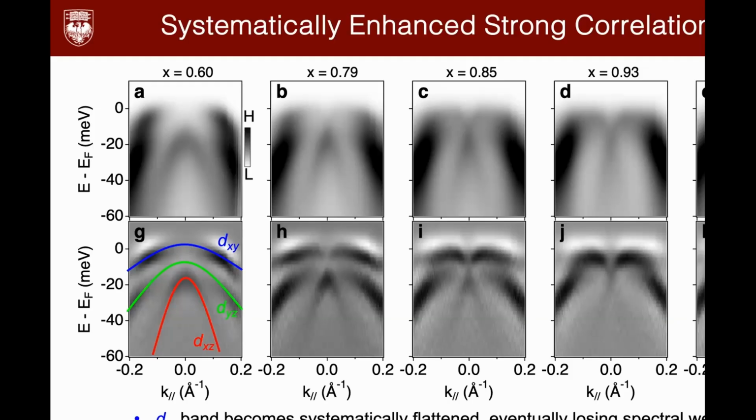One thing I should mention that's very important. The AFM phase, antiferromagnetic phase, has a very strong signature, also a resistivity downturn, right? So you can measure, and we did not see that transition in these samples. So the strain really suppresses the AFM transition.